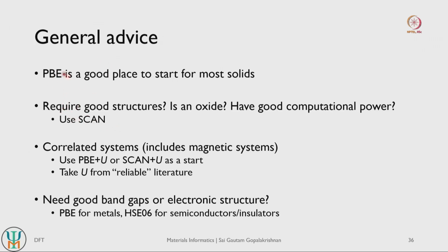So PBE is almost always a good place to start, but let us say you are after good structures. Let us say you want right geometries, right bond lengths, if you have an oxide or if you have good computational power, almost always you should use SCAN to begin with. So if you want good structures, use SCAN. If you have an oxide, try to use SCAN, and if you have good computational power, definitely start with SCAN.